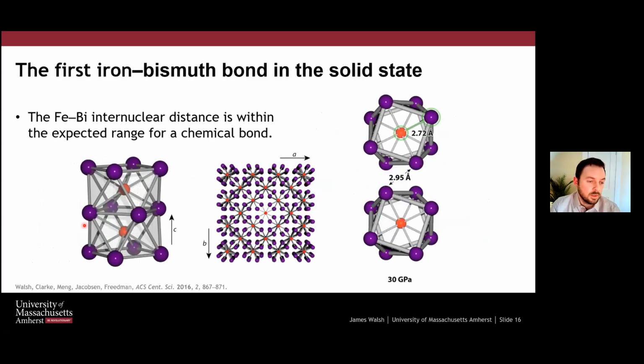And so this is what we get. This is the iron bismuth compound. We published this in 2016. What's exciting about this material, and for me personally, it was exciting because I spent a year doing different kinds of chemistry that went nowhere, was that this is the first iron bismuth bond in the solid state.